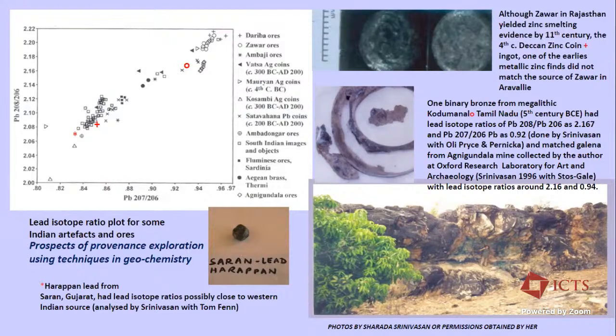The other thing is that though here we're talking about binary bronze, there's no lead added here. But even copper will have some trace of the lead deposit, so what you're looking at here is the copper traces. And here I was talking about zinc smelting, and the fact that downward distillation was the process used in Zawar, where the smelted zinc vapors cooled down radically to condense and get the zinc ingot. So you can see here almost like a condensate.